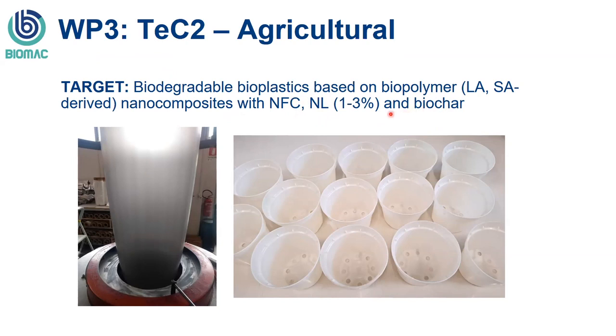And so what you see here are a couple of different relevant agricultural applications. This is a blown film extrusion process in the process of running, actually, and you can see the dark coloration in the material there. And you might imagine using such biodegradable films for mulch films in fields to effectively cover up the soil, to help to prevent weeds from growing and to allow only the plants that you desire to grow to poke through the plastic sheeting. And of course, being biodegradable, this eventually goes away in the field. And in fact, you can even use these additives as a form of enhancing soil quality as well. So that when the material biodegrades, it's actually improving the soil in the process.